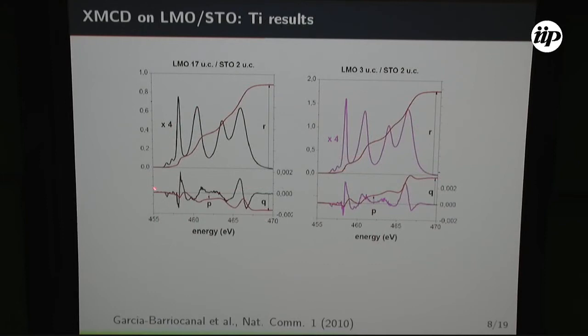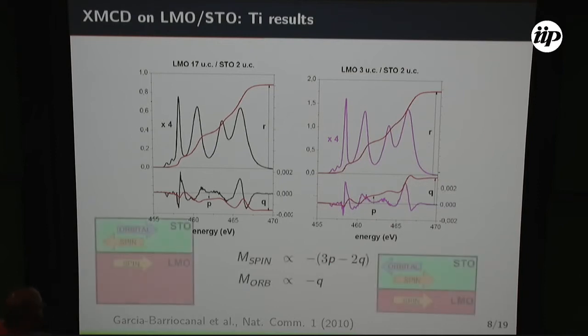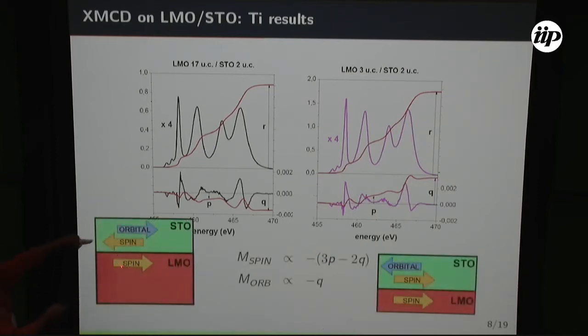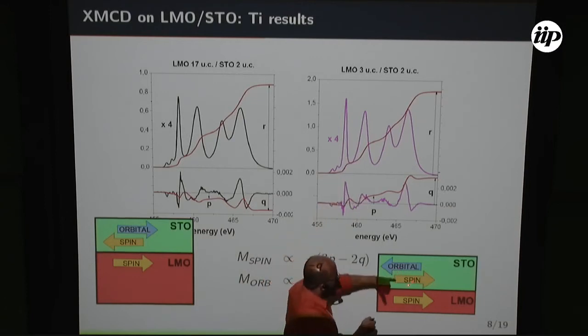Doing the same for the titanium. The titanium is very tricky to measure dichroism, but we did. And here you see that the integral is not 0. So the orbital momentum at the titanium site is not quenched. I cannot tell you how much, except if we do some simulation. And playing with these values of these integrals, I can tell you that in one case, the spin moment of the STO is anti-parallel to the manganite. On the other extreme, for the thinner, the spin moment of the STO is aligned with it.